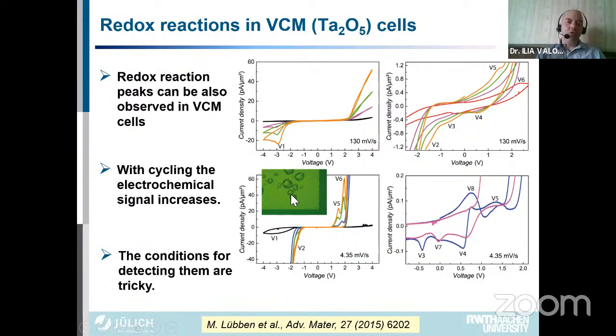So you don't need to specially expose to some special moisture level. It's enough, let's say during the ALD process, there are enough protons within the device, and they can form, let's say, hydrogen, or simply during device preparation steps, you have some exposure to moisture, or even environmental moisture is enough to penetrate after 10 to 15 seconds, even in encapsulated devices, because most of the encapsulation is not sufficient to stop the natural penetration of moisture.